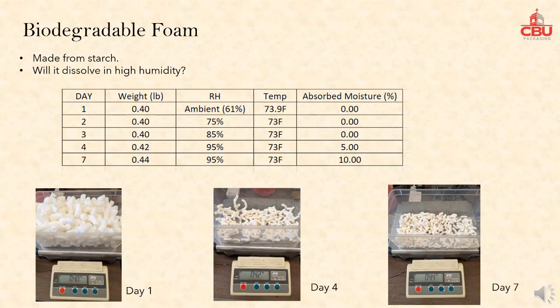The pictures shown on this slide include the foam on day 1 with 61% relative humidity, day 4 at 95% humidity, and day 7 at 95% humidity with extended period of time. The percent moisture absorption after 7 days was only 10% without any disintegration of the foam. Foam pieces only shrank and became denser.